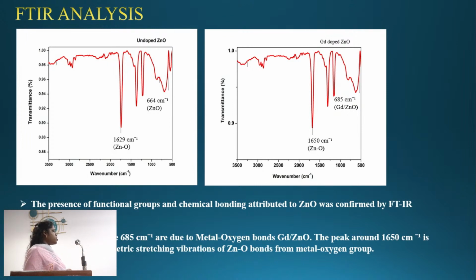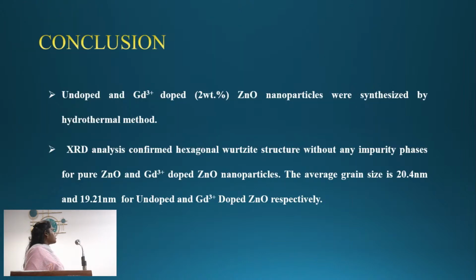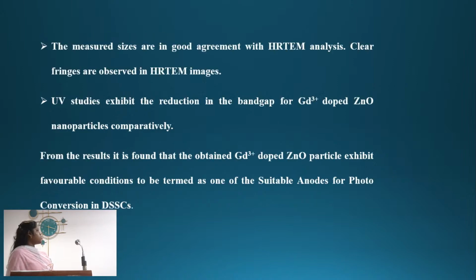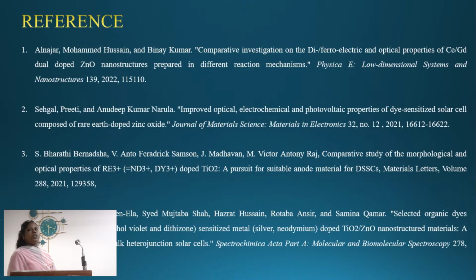1650 centimeter inverse and 1629 centimeter inverse is asymmetric stretching vibration of ZnO bonds of metal oxygen groups. Next one is the conclusion. Undoped and gadolinium doped ZnO synthesized by one-pot hydrothermal method, and XRD analysis confirmed hexagonal wurtzite structure, and the average grain size is 20.4 nanometer and 19.21 nanometer for undoped and gadolinium doped respectively. The HRTEM is in good agreement with XRD results.